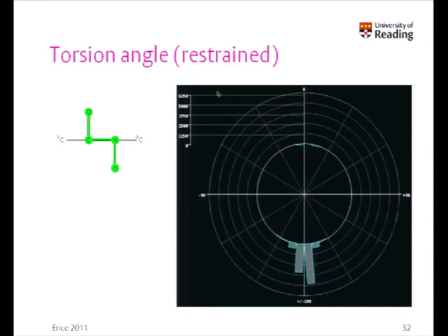Here's an extreme example of a torsion angle that the automatic input of a global optimizer may not pick up on, and this is an amide bond. It might just pick that up and identify it as a single bond and say that you would rotate it, whereas any self-respecting chemist would recognize that the chances are that's going to be trans at 180 degrees, and that's what the database tells you. So you can actually go in and modify the internal coordinates that have been created by the program and fix it at the highly likely value of 180.